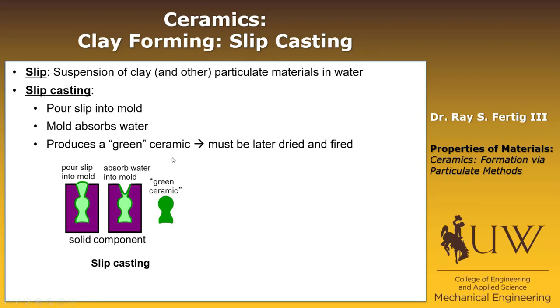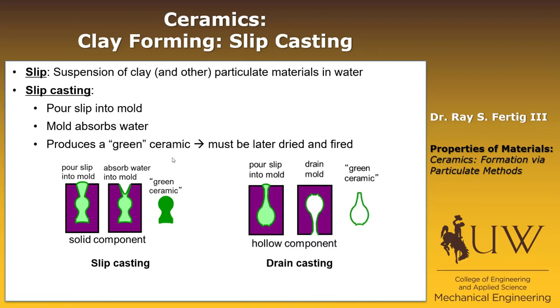There's a complementary approach called drain casting, which is really similar. You pour the slip into a mold, except instead of expecting the mold to fully fill, you just allow there to be some thickness of coating around the edge of the mold to get a hollow component. So that's one method of forming a clay product.